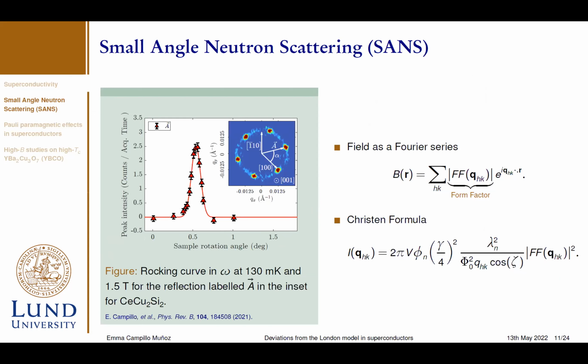Once we have our experiment, we want to obtain physical quantities that are going to help us characterize these superconductors. Usually, we rock our sample around the neutron beam to fulfill the Bragg condition, so that we have a Bragg reflection on one particular point of the reciprocal space. The information that this Bragg reflection can provide us is given by the integrated intensity that we can measure from this rocking curve.